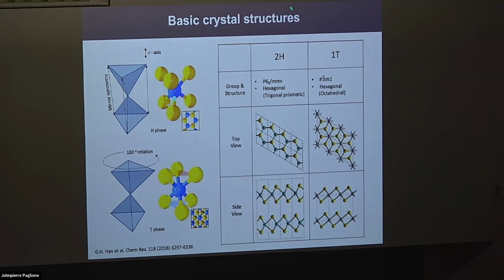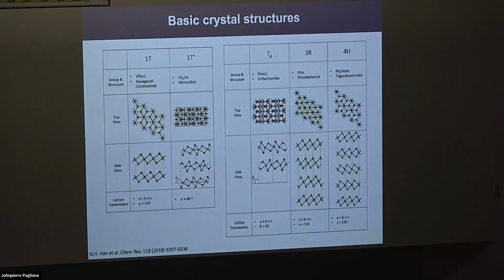Okay. So this is the 2H breakdown in crystal structure, but this T phase can also be broken down and can go from a threefold to twofold symmetry. Essentially, what happens is you can get these transition metals to dimerize, and this leads to distortion in the chalcogen outer plane, giving rise to different stacking sequences as well. And so the 1T phase breaks down into this T prime and Td phase. Examples of the T prime and Td are tantalum, tungsten and molybdenum ditelluride.